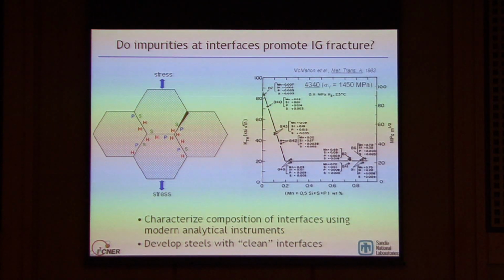What Charlie found is that the two elements that were most important were manganese and silicon. The way I understand his papers, it was still the phosphorus and sulfur which could enable the intergranular fracture, but somehow it was the manganese and silicon which was helping these elements segregate to the grain boundaries. I don't think Charlie ever fully understood or explained this, so I think it's a really rich area we could try to look into.